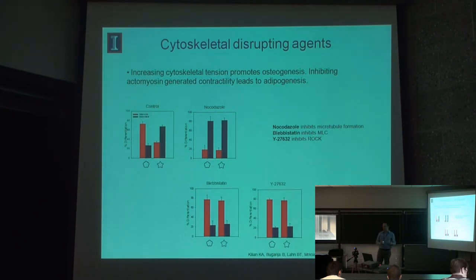And so we've lost the shape dependence by basically using a sledgehammer to knock the contractility up of these cells. In contrast, you can do it with other molecules. So we inhibited myosin light chain with blebbistatin, and there we saw the same trend, but this time we see all of the cells turn into fat. And by blocking Rho kinase, which is an important player in the contractility of cells, we also saw abrogation of this trend, all fat. So this is consistent with our story, that these subtle geometric cues can influence actomyosin contractility. And by knocking it out, we can get rid of the shape direction.